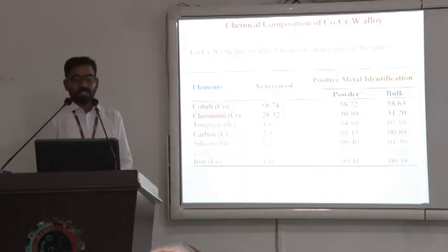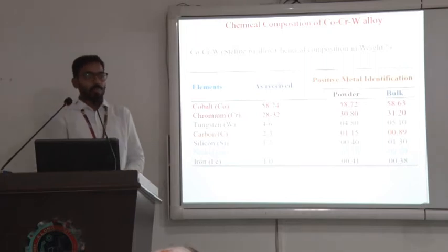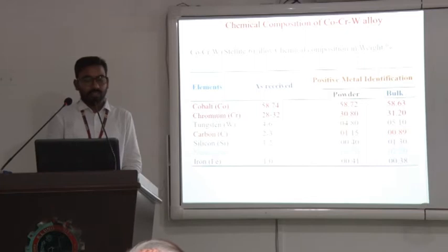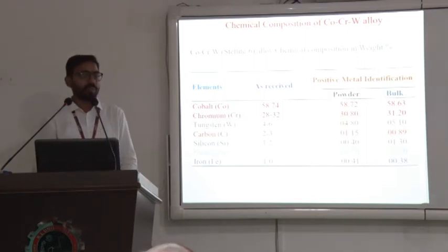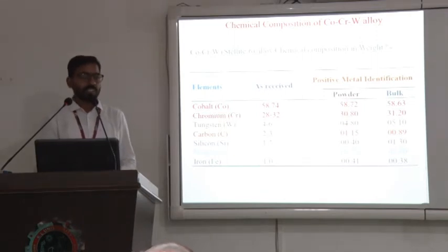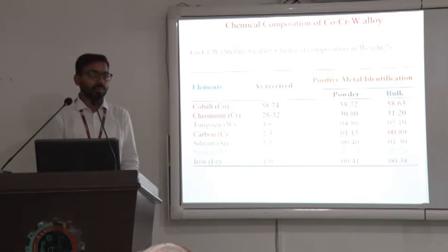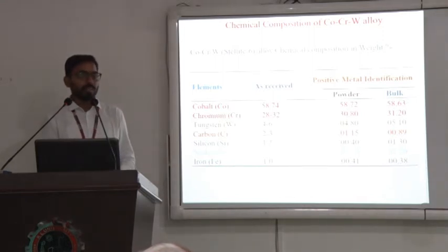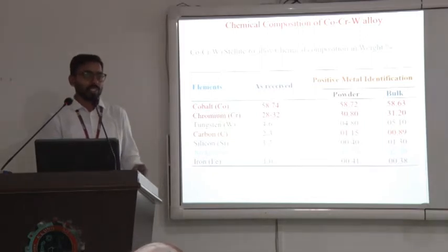Chemical composition of the cobalt chromium tungsten alloy: elements in cobalt-based alloys as received from the specifications. The composition was received from the vendor, and later we conducted XRF analysis, a positive metal identification method, which is non-destructive testing, to test the powder and samples for any modifications after LENS deposition.